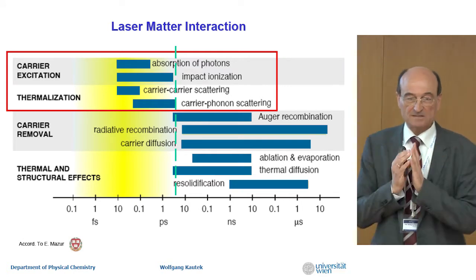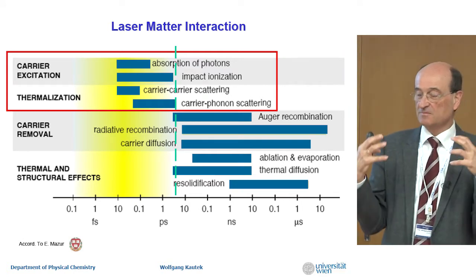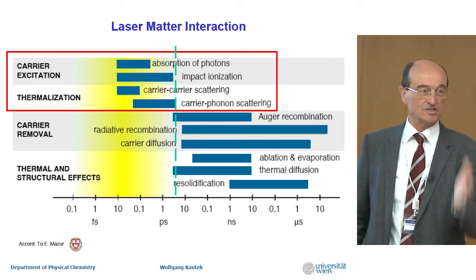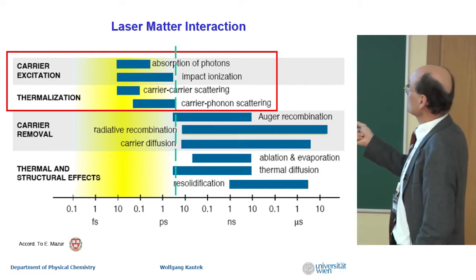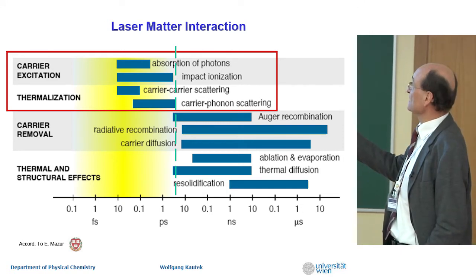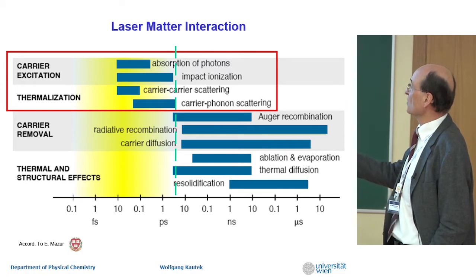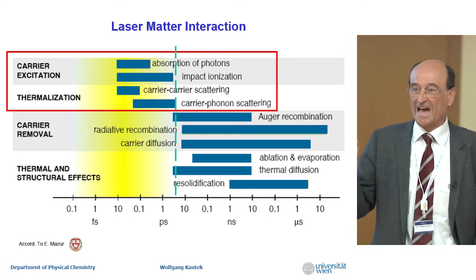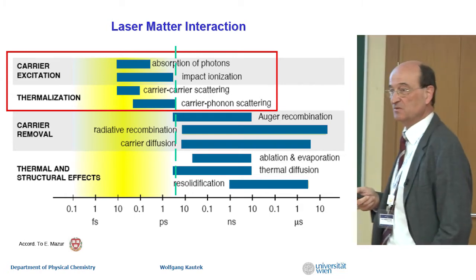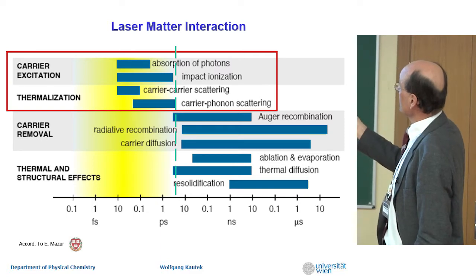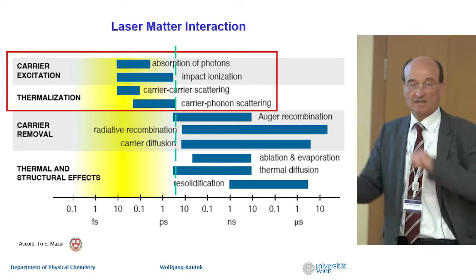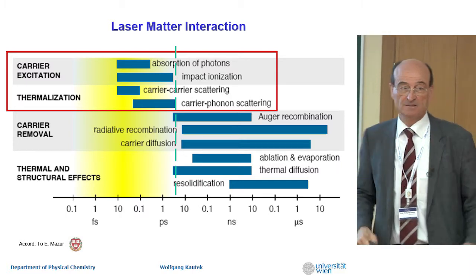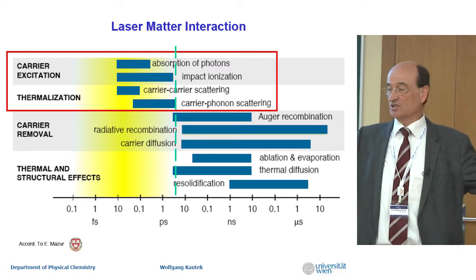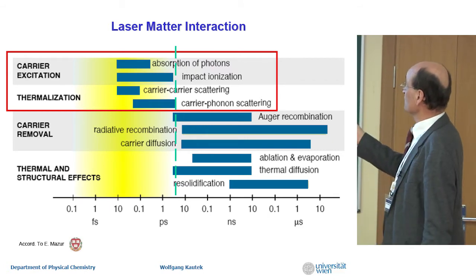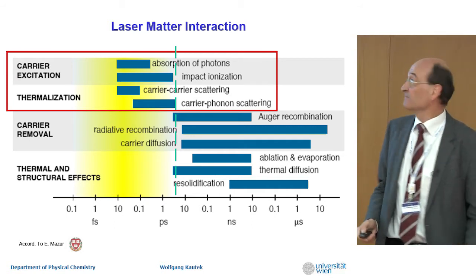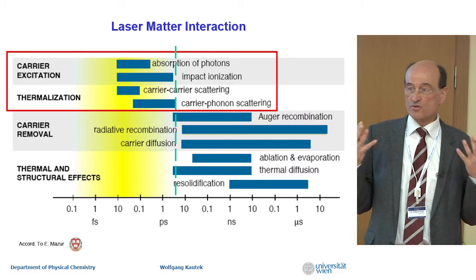And now we are looking at the electronic system and the atomic system in the course of time after interaction with electromagnetic light. So the absorption of photons is in the beginning, and it's certainly faster than, I would say, 10 or 1 femtoseconds. In the meantime, people are working with attoseconds and looking at the fate of electrons between orbitals. Now, then we have a phenomenon called impact ionization, then the carrier-carrier scattering, and at the end, the electrons dissipate their energy to the lattice, and that's called the carrier-phonon scattering. And that's the end of a domain which we call non-thermal interaction.